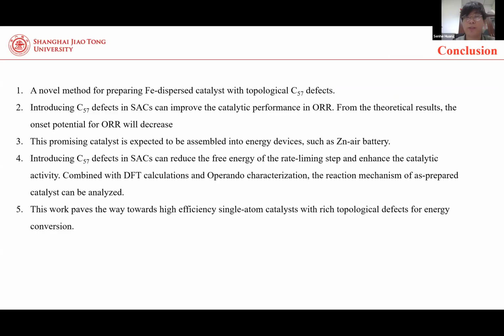Now I'd like to make a conclusion for my presentation. First, we propose an effective strategy towards atomically iron-dispersed and topologically defective porous carbon nanosheets by using azulene-dominated materials as precursor. So the as-prepared catalysts exhibit promising performance in oxygen reduction reaction and in zinc air battery. The results show the potential of this catalyst in practical application.